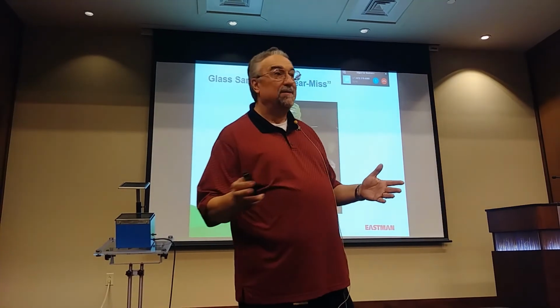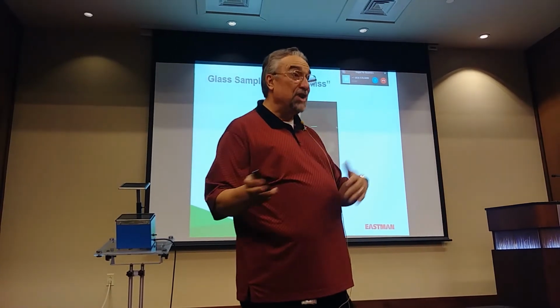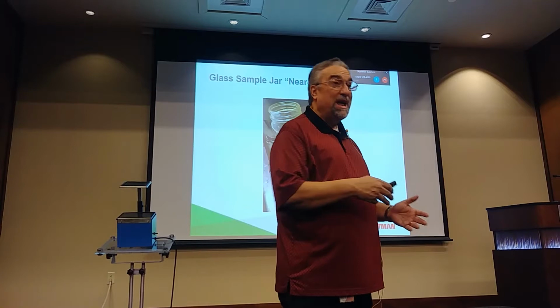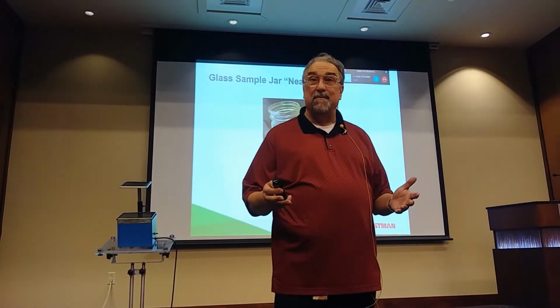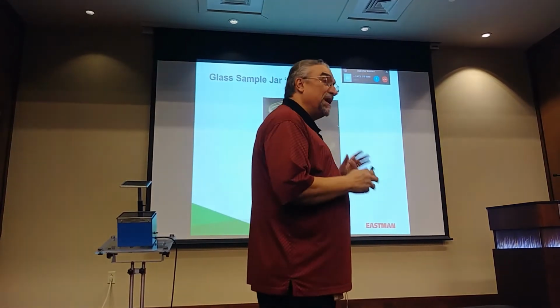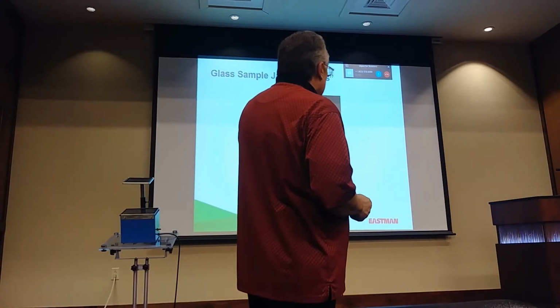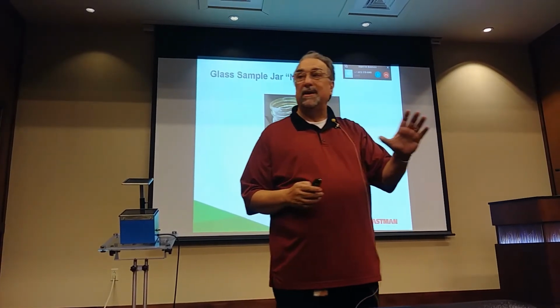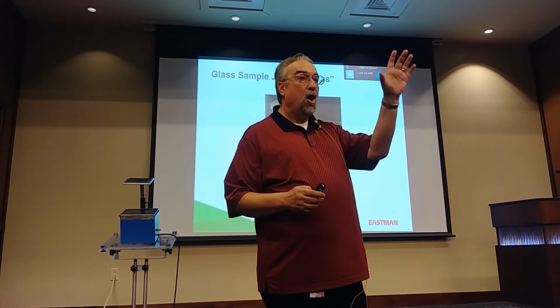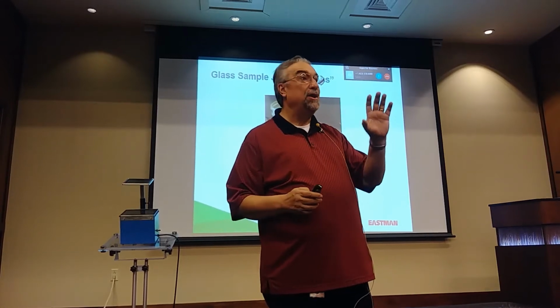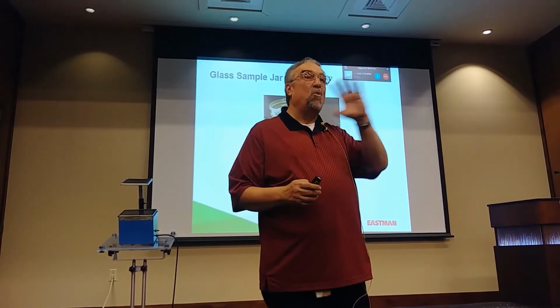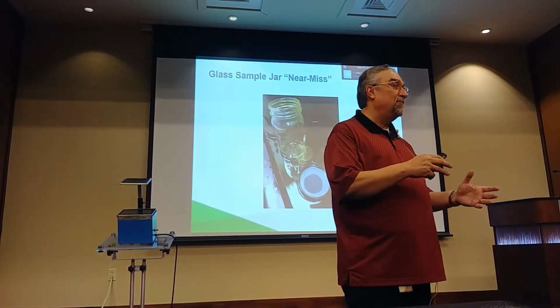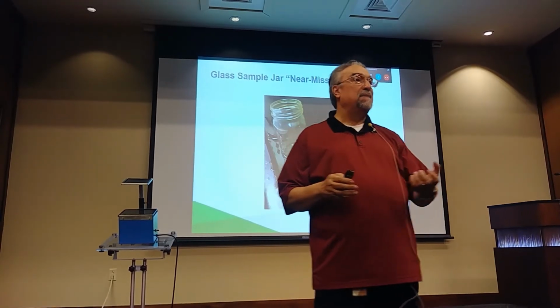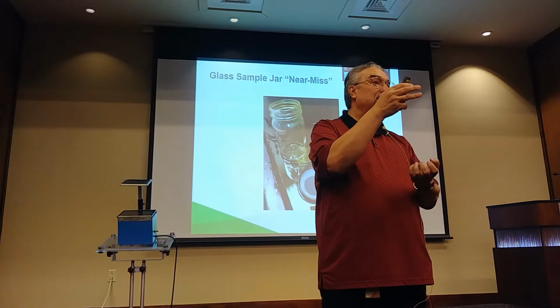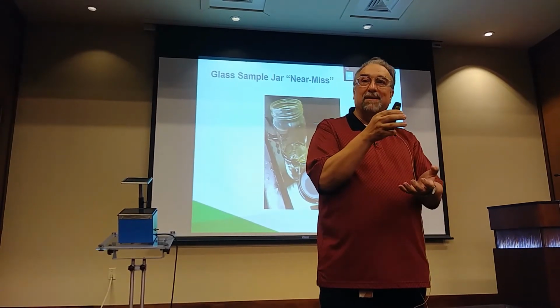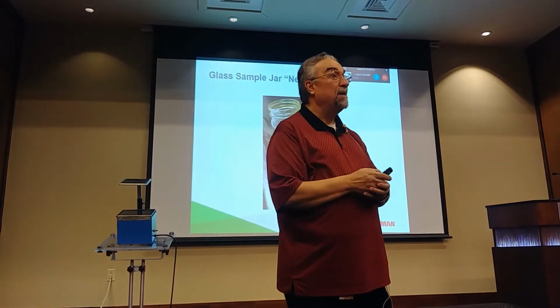Now, the coefficient of expansion played a part in this. And then something called the shock factor played a part in this. And what happened next was the bottom fell out and I had a big mess to clean up. But let me explain what happened. The glass was cool because it was sitting in the hood, and it's at one temperature, all uniform. Glass does not like non-uniformity, okay? So it was there, all one uniform temperature. And when I poured that hot resin into it, it heated the bottom of it faster than the rest of the glass could account for the expansion. And it popped that bottom out, just as pretty as if I had scored it and broke it on purpose.